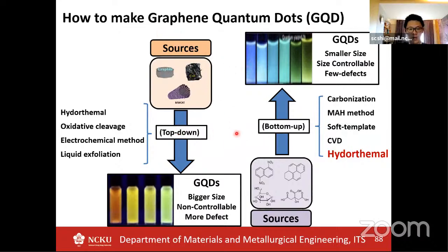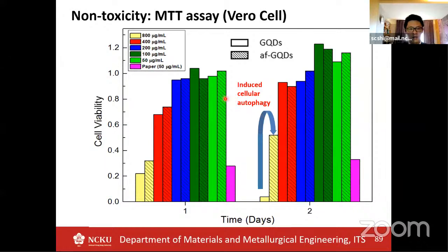There are two major ways: one is top down, one is bottom up. Here we use the glucose from the hydrolysis of cellulose and process it by the hydrothermal process, and we can have the graphene quantum dots. Because the graphene quantum dots are made from glucose, they are nearly non-toxic like this. So the cell viability is really high. Even at a very high dose and for a very long time, 2 days, the viability is nearly one. So this is a very good material or template for bio applications.